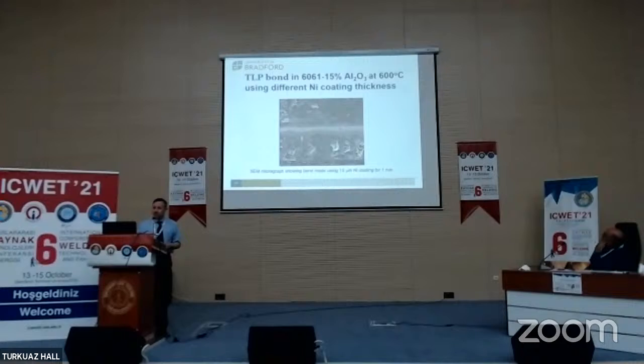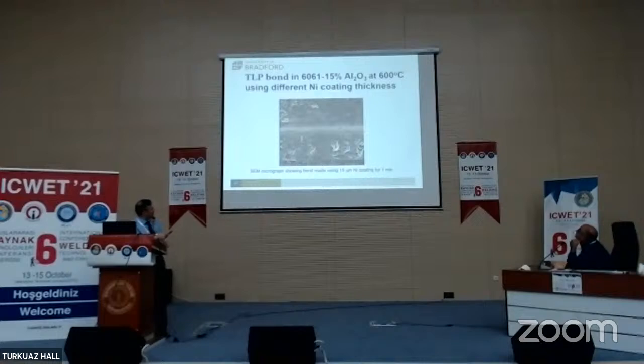So again, this is now another example of what happens if we try to control the bonding solidification process by using a dispersion of alumina. Alumina being a ceramic dispersion. So what we see is that for very thin coatings, 15 micron nickel coatings, we form a eutectic between aluminium and nickel. And for 1 minute, we can see that the joint region has formed. And interestingly, the particles are not lost from the joint. The particles are still present here inside the joint region. We would expect the particles, like the professor in Malaysia said, the particles are less dense, they would be lost from the joint region. But this is something interesting.